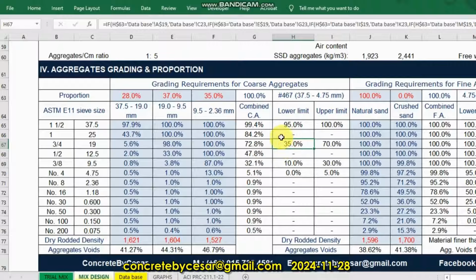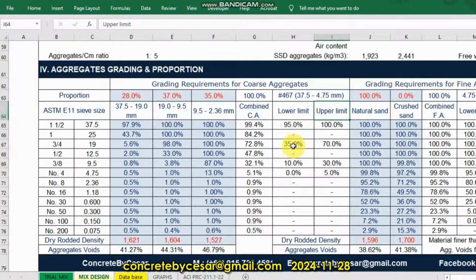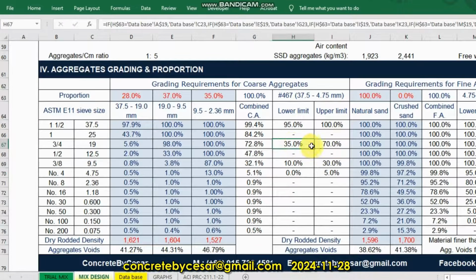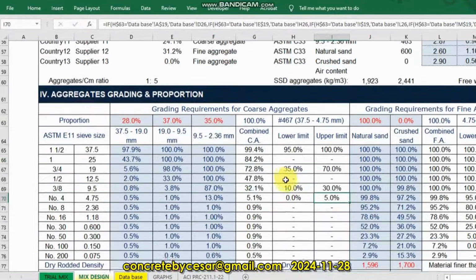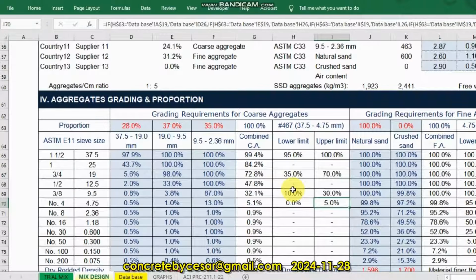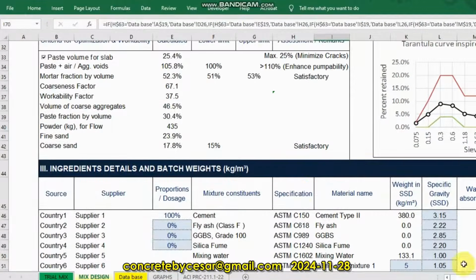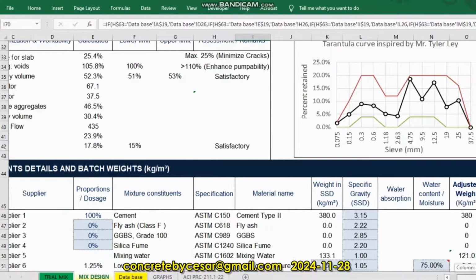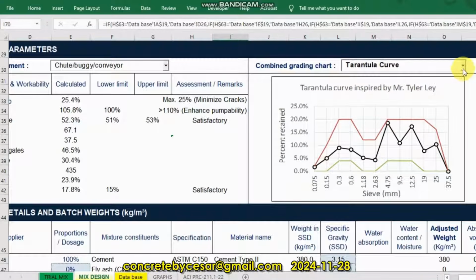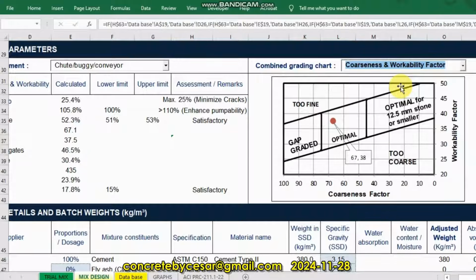You can see also that this is the lower limit and upper limit, and you notice that we are exceeding the limit. The 70% we exceeded, 72.8%. Instead of 30, it became 32. So I just want to point out that in other cases, like for example in my case, the most important for them, for the specification, is to be in line with this chart.